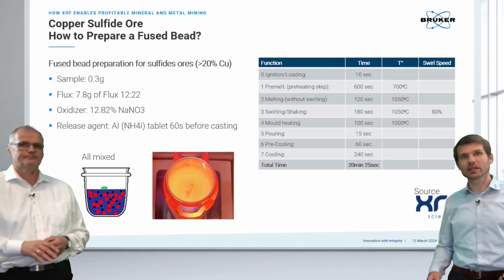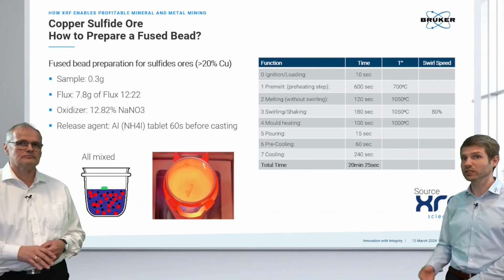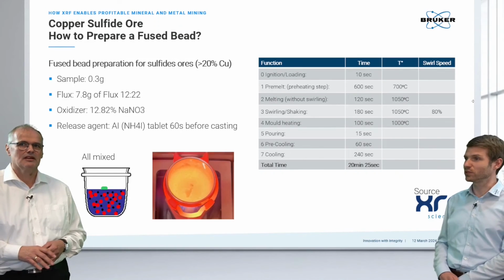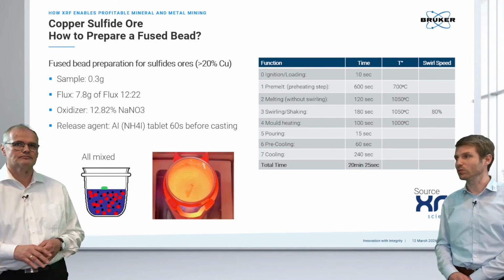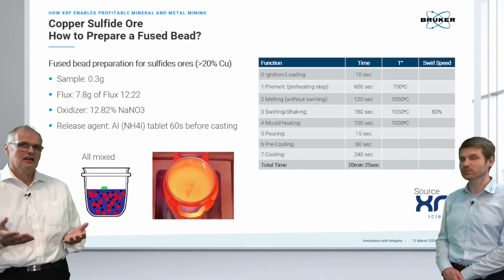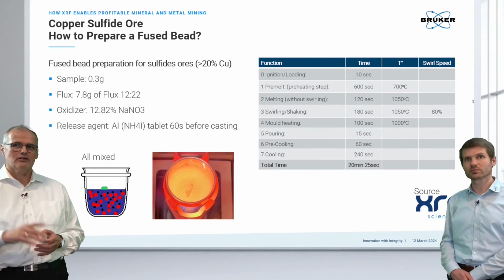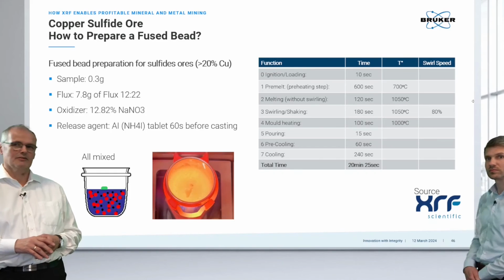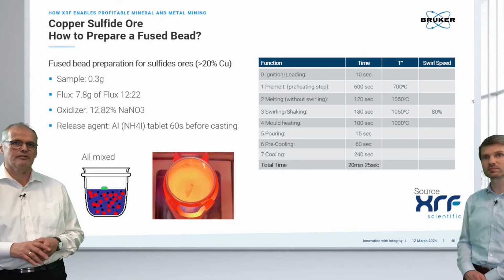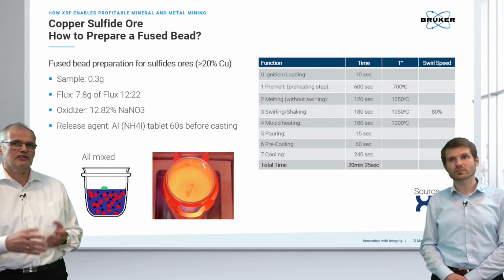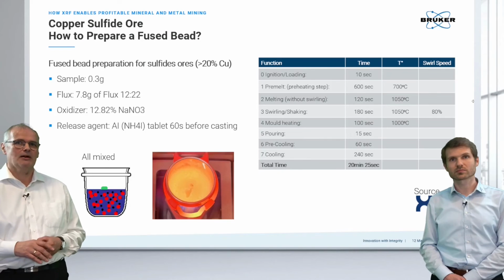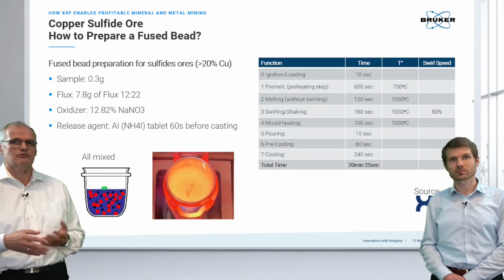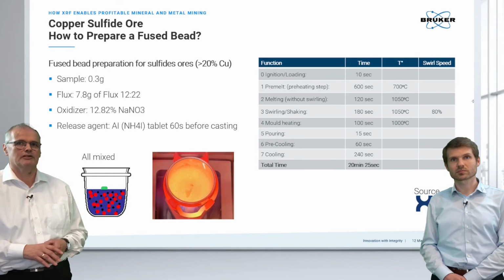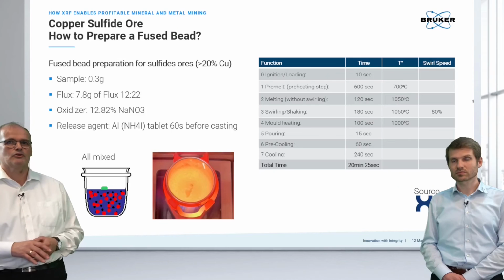Mm-hmm. Let's maybe look a little bit further into a recipe for fused beads. We have now heard a few words about that. It's quite complex for this material. Yeah, so again, our friends from Australia, XRF Scientific, they have come up with a recipe. So actually, you take a little bit lower amount of sample. You take a flux ratio between lithium tetraborate and lithium metaborate of 12 to 22.